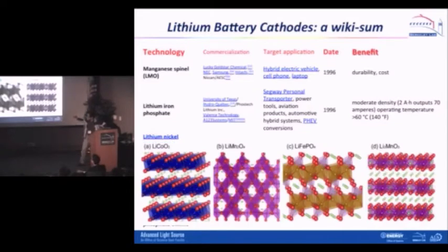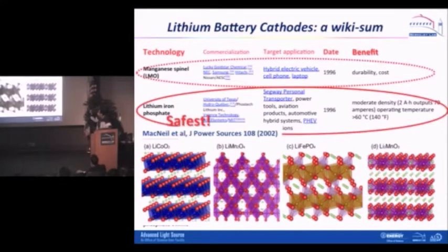All those transition metal oxide materials have a basic structure. When the lithium goes in and out, the lithium takes a particular space, either layered, a 1D chain, or a 3D type of diffusion channel. I will talk mainly about lithium iron phosphate, which is considered to be the safest material at this moment to be used in the electric vehicle. However, it is very interesting because this is the only material at this moment with only a 1D channel for lithium diffusion, which is typically considered to be very bad for a lithium-ion battery.